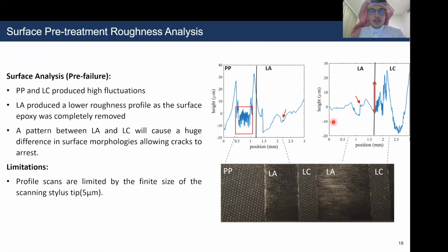It is worth noticing that at the interface between LA and LC, there is a high change in the surface morphology, and this can be an area of interest because this can be an area for the crack to arrest. When the crack is moving in the LA and then it faces a huge change in the morphology height, it would be difficult for the crack to propagate further, and it would require more energy. So this can be a cause for the cracks to arrest.